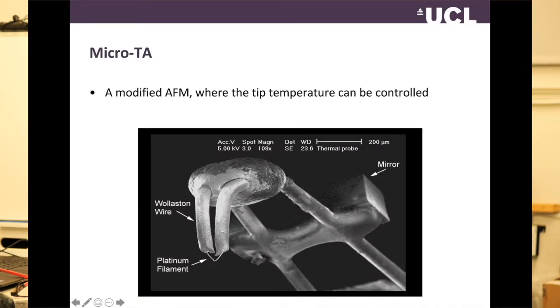Right, this is the tip that I was just talking about, which has been modified to measure thermal conductivity. It's essentially just a wire which has been insulated, and the insulation has been removed right at the tip, which is where it touches the sample. So it allows you to measure thermal conductivity.